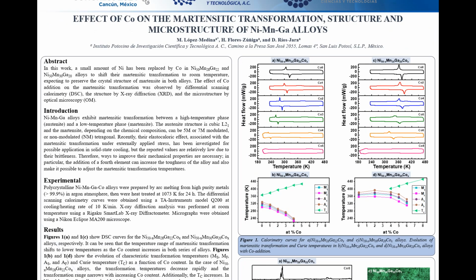Figures 1A and 1C show calorimetry curves for the Ni50-xMn28Ga22Cox and Ni50-xMn30Ga20Cox alloys, respectively. It can be seen that the temperature range of martensitic transformation shifts to lower temperature as the cobalt content increases in both series of alloys. Figures 1B and 1D show the evolution of the characteristic transformation temperatures MS, MF, AS, AF, and the Curie temperature Tc as a function of cobalt content.